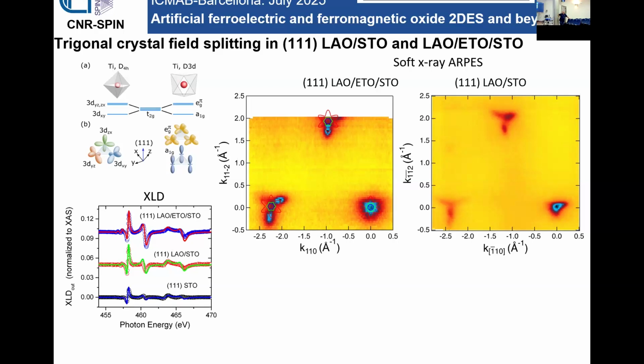Experiment, okay. But the model with a single band with large trigonal splitting would require using a full Hamiltonian with all the bands, and then you have to put the Fermi level there and calculate the contribution. So also to explore this kind of physics, putting europium titanate should work, no? According to the ARPES experiment. This was just luck in some sense, because there is some distortion in the different titanate which makes the band split. Okay, thank you, Marco.